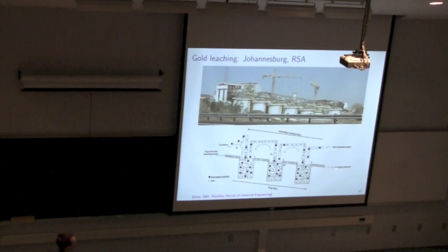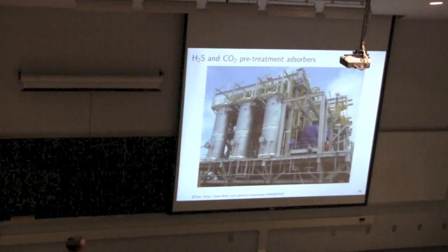Then those tailings then go and they simply take that sand. Now we've removed your gold. So the tailing, the pulp that you have coming in here, you've got gold in the order of 6 grams per ton of gold. So you have to mine a whole ton of soil or rock to get 6 grams of gold. By the time it leaves there, it's less than 0.5 grams of gold. And then that simply just gets pumped back into the ground or deposited in big tailings dams. Okay, so that's the principle there in that example.